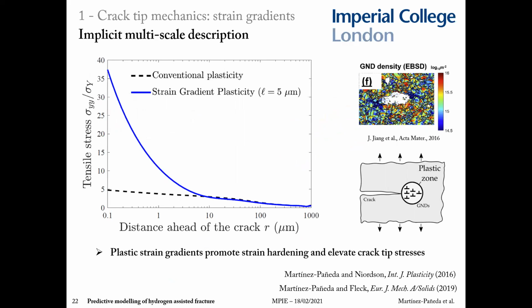Because if you have a crack in a specimen, independently of the size of the specimen, you're going to have a plastic zone that is physically small and that contains strong spatial gradients of deformation. So you're going to see those local hardening mechanisms that we saw before, the same way you see them in indentation. And today you can measure very precisely GND densities ahead of cracks and inclusions. And what you see when you model crack tip fields with strain gradient plasticity is what you see in the slide. Here I'm plotting the tensile stress versus the distance ahead of the crack tip. And you can see that far away from the crack tip, both conventional plasticity and strain gradient plasticity agree. But as you approach the crack tip within tens of microns, strain gradient effects start to play a role, and then you get a stress elevation as a consequence of those local hardening and strengthening mechanisms. And differences are quite significant if you look at 1 micron ahead of the crack tip, which is the critical distance for hydrogen embrittlement.